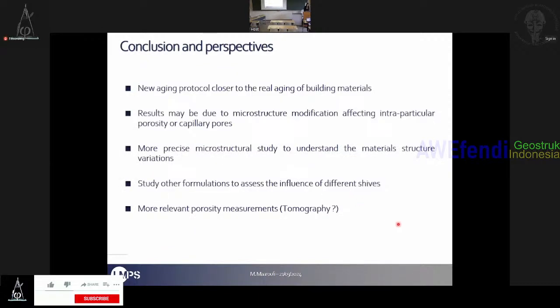So, as a conclusion, but also a lot of perspectives, we tried to elaborate a new aging protocol which would be closer to the real aging of building materials and less severe than what we can find in previous works. The results may be due to the microstructure modification, especially the intraparticular porosity and the capillary porosity. We should have some more precise microstructural study to understand the real microstructure variations of the materials, and maybe study other formulations to assess the influence of different aggregates, for example.